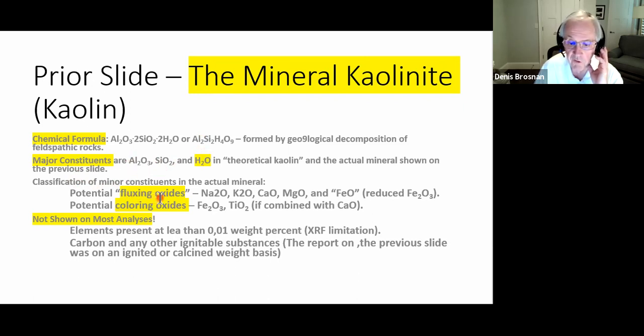And some of those could be fluxing oxides like soda, sodium oxide, potassium oxide, calcium oxide, which I call lime all the time, magnesia, MgO, and FeO, if it were present in that valence or oxidation state. In other words, reduced hematite or red iron oxide becomes wustite or FeO. We have some coloring oxides that are there, the irons and the titania. Sometimes the lime will combine with titania and form specific colors called sphenes. Those are the mineral forms.